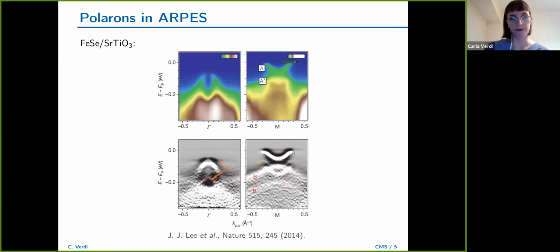There are other very famous examples. For example, this was published in Nature, and it deals with monolayer iron selenide on strontium titanate. And this is a hole band, and this is an electron band. It's not very clear from the ARPES intensity map itself, but when you look at the second derivative plot, you can see more clearly that there is a band and the satellite can be resolved apparently also for the hole band, although you can see it less clearly.